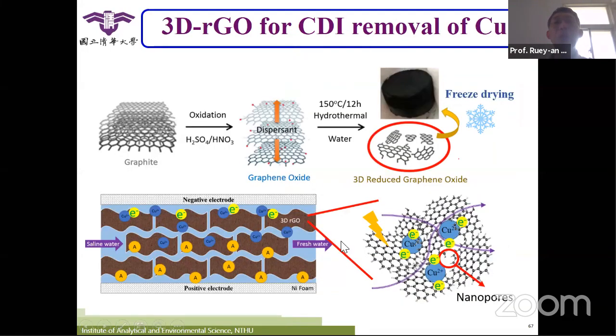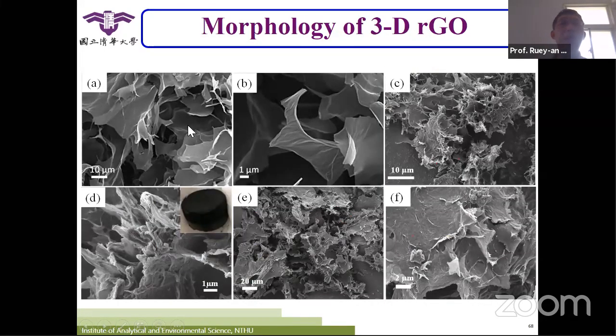We also use the three-dimensional structure for CDI. This is its morphology here. Its pore is high, so the penetration will be good. In the SEM image, you can see that we have other pores going inside, so the water penetration and electrolyte penetration will be good.